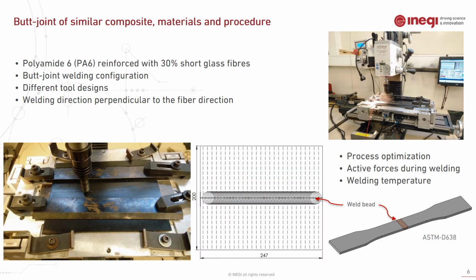For this study, polyamide 6 reinforced with 30% short glass fibers was chosen to weld in a butt joint configuration, and we studied different tool design geometries and their effects on the weld quality. The weld direction was perpendicular to the fiber direction, as you can see in the picture. On the top right picture you can see the final setup for welding, and on the bottom the specimen geometry